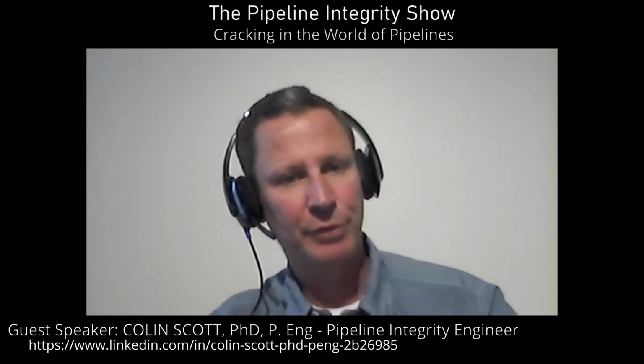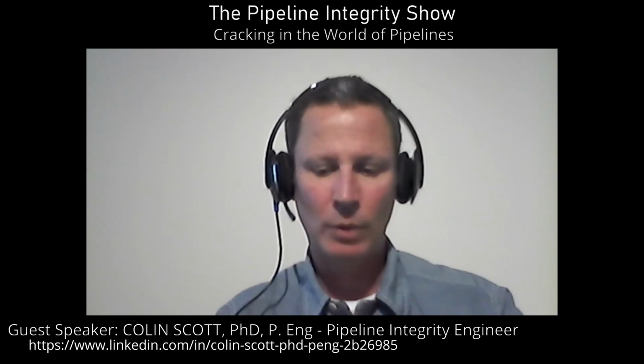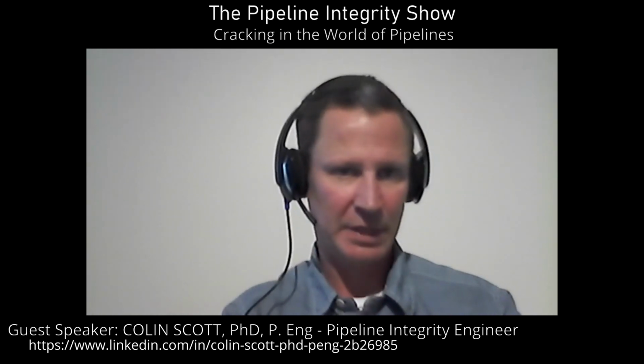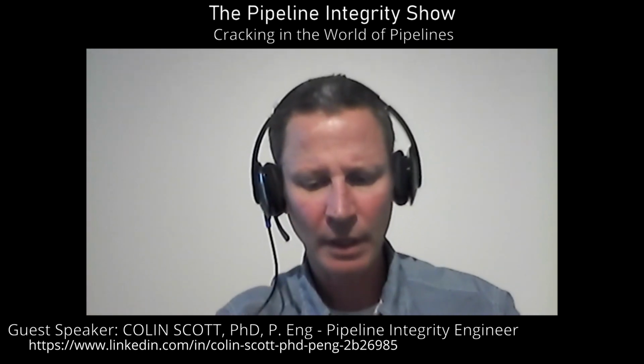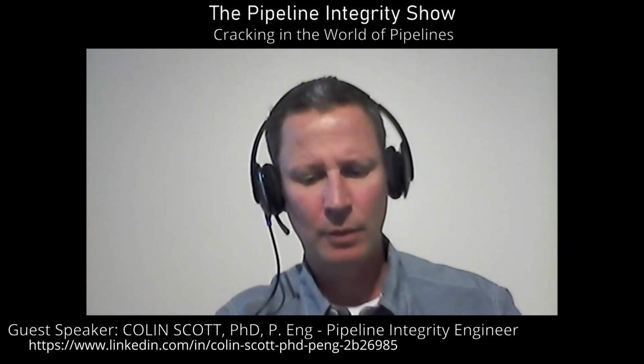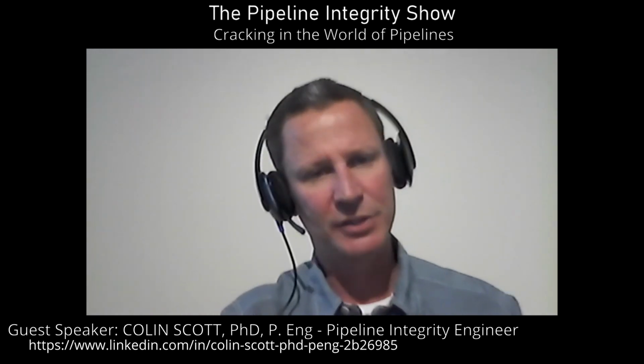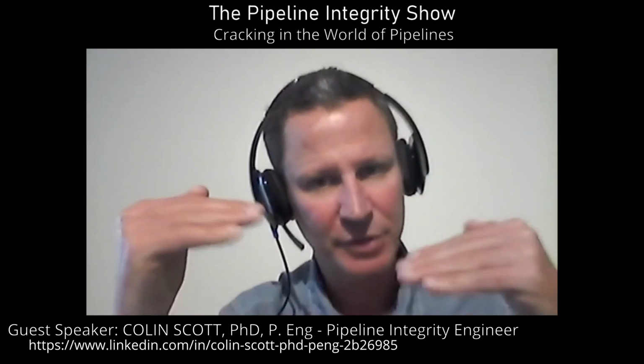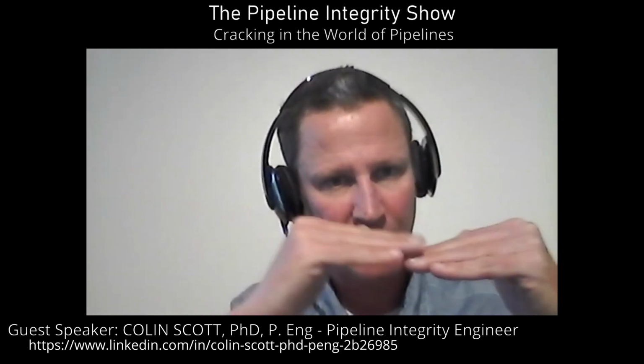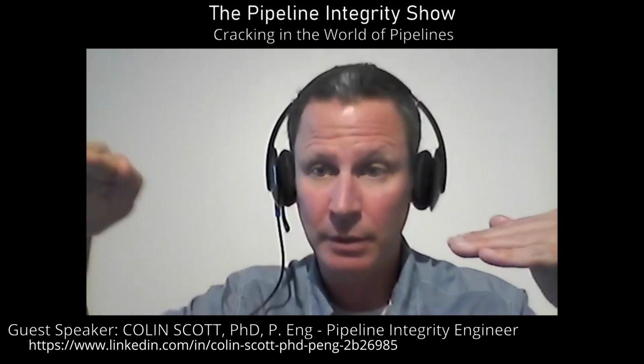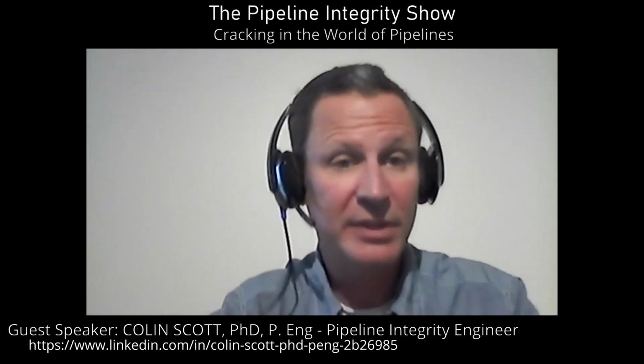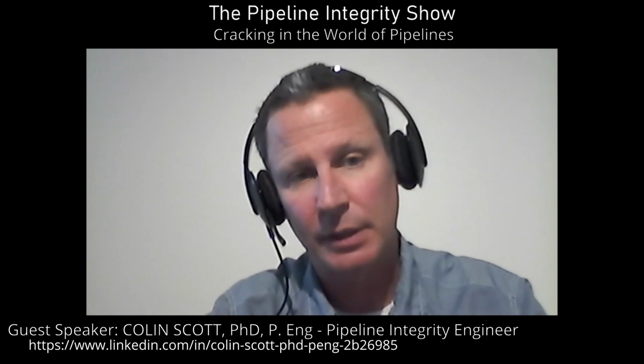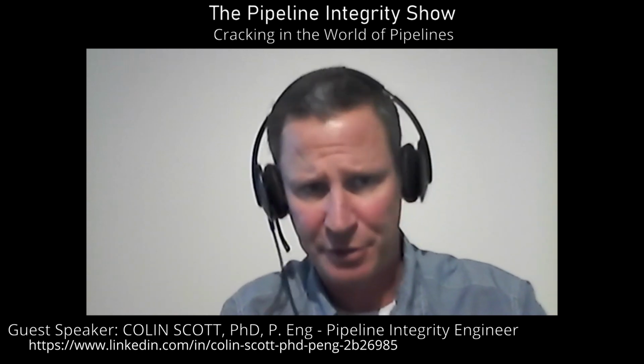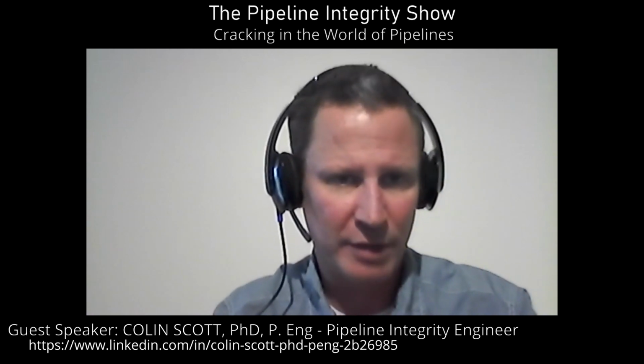You can also look back at your recent pressure history, and you can say to yourself, well, we know we survived to whatever pressure over the last 2 or 3 years maybe. And you can say to yourself, well, we can do that same calculation again and figure out what's the critical crack depth as of 2 years ago. Now, once you've got those two values, you can basically interpolate the Paris law coefficient, and you can figure out what's your worst case crack growth, and then you can extrapolate that, with the assumption that you're going to keep going with similar pressure cycling. And when you do that, you find out you've got several years to play with. So I think that gave the operator some comfort.